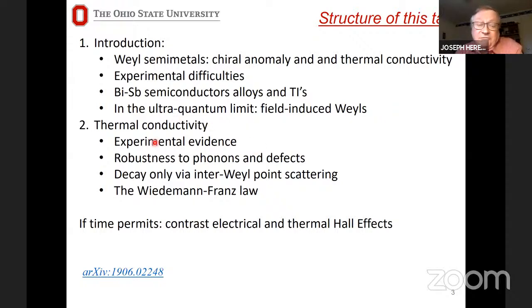The main bulk of my talk is experimental evidence for anomaly in the thermal conductivity. I will show you that this is robust to phonons, robust to defects. So we would like to see this as being topologically protected, but I'll show you data and it's up to you to judge. I'll show you that we think the decay of what we observe with temperature is really only by inter-Weyl point scattering, by thermal excitation from one Weyl point to the other Weyl point, and not by an interaction with phonons or impurities.